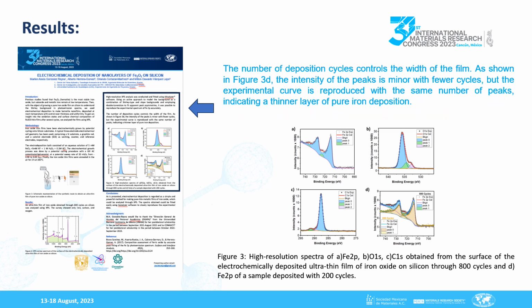After conducting the experiment, the relationship between the number of cycles and the width of the film was analyzed. The results, as shown in Figure 3D, indicate that a lower number of cycles lead to a decrease in peak intensity. Because the fitted spectra show the same number of deconvoluted peaks, the film only presents a thinner pure iron-3 oxide deposition.